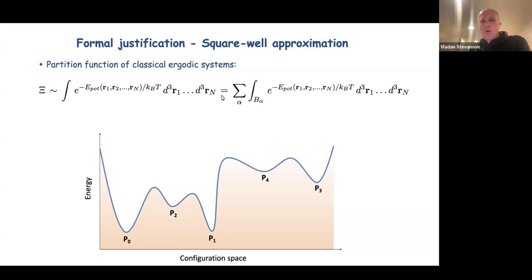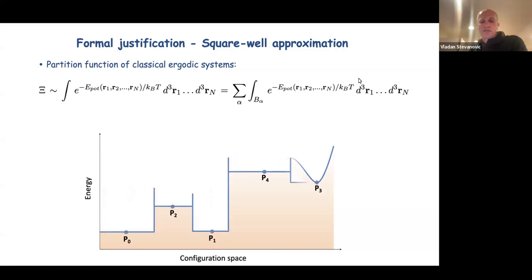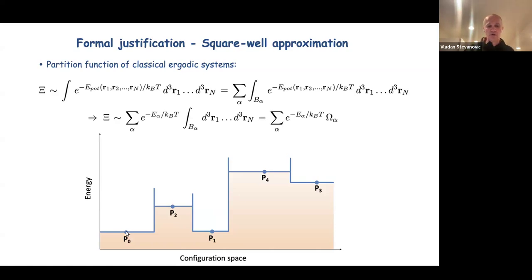And then one can, as it's usually done, separate this integral. So split the domain of integration into different basins of attraction and express this integral as the sum over different basins of attraction, where within each basin you have the corresponding integral. If one makes an approximation like this, going from the actual potential energy surface into some kind of a square well approximation, then within each well the energy assumes a constant value. So the exponential can be taken in front of the integral with a value that corresponds to the actual value at the local minimum. And what remains under the integral is nothing but the volume of configuration space occupied by a given basin of attraction.